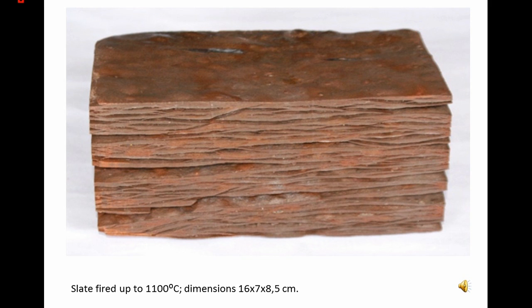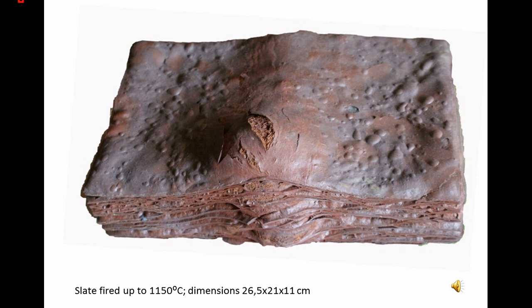Submitted to 1150 C, the piece texture gets thinner and dense, and the shape of the final product is quite different from the original shape. Also, the internal structure made of overlapped laminas changes to a spongy structure. The external surfaces show a more uniform gloss, reminding the gloss of leather, and its relief is accentuated. The skin shows ragged areas, with peepholes through which one can see the characteristic spongy interior mass. The most internal zone of this spongy structure exhibits black color and, as it gets close to the surface, changes to gray and to light red very close to the surface.